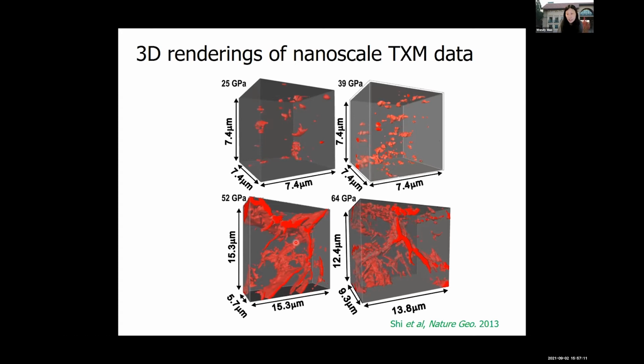We also see that the molten iron is efficiently wetting the surface of the silicate grains. You can almost see them outlining them. So we see a pretty dramatic change in the potential percolative ability.